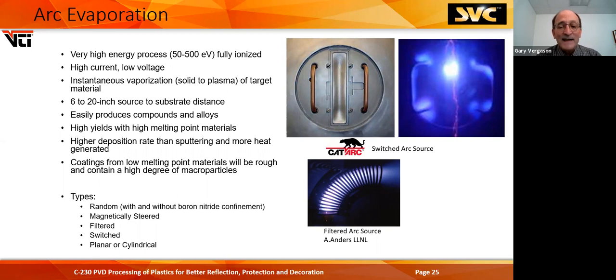So instantaneously, that solid cathode goes from a solid to a plasma and transports across the vacuum space. We usually have a 6 to 20 inch source to substrate distance. It depends on the temperature handling of your substrate. It easily produces compounds and alloys. You can't poison one of these targets. It loves to operate in a poison mode because that greatly increases the melting temperature of the surface, which makes the arc spot go faster. But if you're using discrete anodes or even a chamber's anode, you can poison your anodes. And when you lose that electron return path, these will turn off.